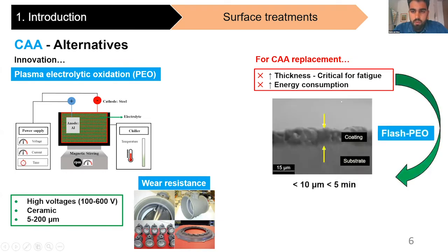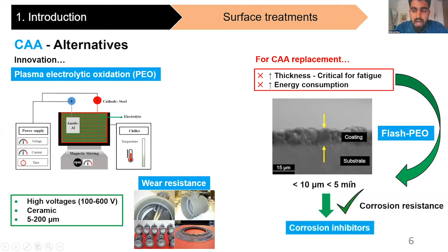So a possible way to overcome this limitation is the flash PEO process, which consists in the formation of PEO coatings with low thickness value using low treatment times. And a possible way to increase its corrosion resistance is the incorporation of corrosion inhibitors into the coating structure.